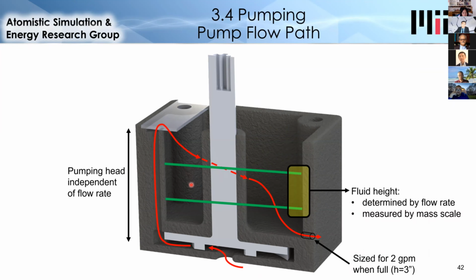And so here, as I pump faster, this green fluid level will rise to the second level, depending on the flow rate. And then the fluid leaks out of this bottom hole. So in this case, all I need to do is measure the weight of the pump to determine the flow rate. So when I stop pumping, the pump will get lighter. When I start pumping, it will get heavier. And I can actually experimentally determine the exact flow rate based on this information.